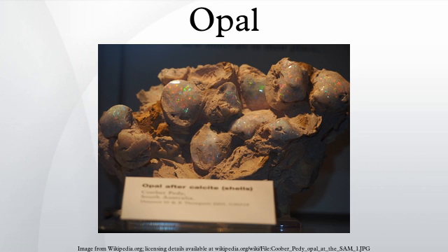Precious opal. Precious opal shows a variable interplay of internal colors, and even though it is a mineraloid, it has an internal structure. At micro scales, precious opal is composed of silica spheres some 150 to 300 nanometers in diameter in a hexagonal or cubic close-packed lattice. These ordered silica spheres produce the internal colors by causing the interference and diffraction of light passing through the microstructure of the opal. It is the regularity of the sizes and the packing of these spheres that determines the quality of precious opal.